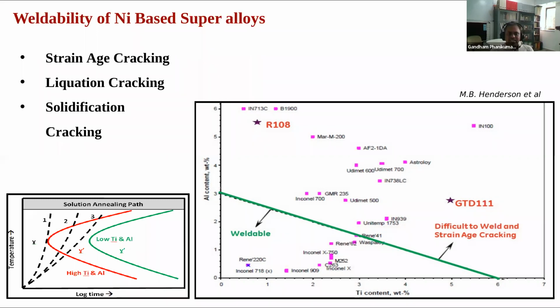And liquation cracking is a bit different, because liquation cracking is occurring because of a eutectic that is melting upon reheating. Okay, so during solidification it is occurring, then it's a solidification cracking or hot cracking. But during reheating, if it is occurring, because a eutectic region has molten, that's called liquation cracking. Now, strain age cracking is a totally different concept.